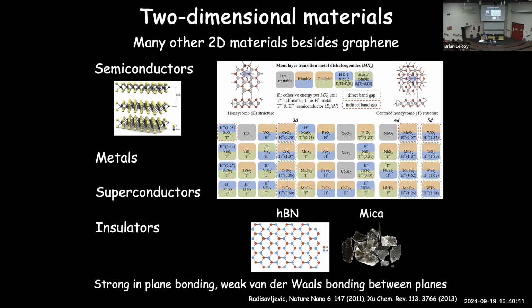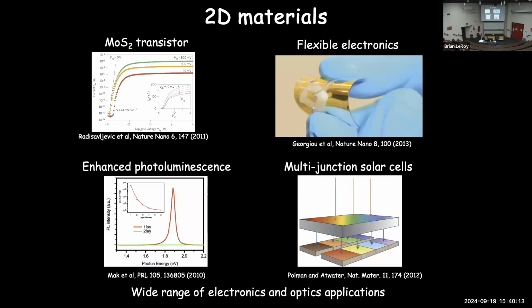And so with this wide zoo of materials, that has led to a wide range of electronic and optical devices using these materials. The graphene I showed you before does not work very well as a transistor. It's not a good semiconductor, but if you take something like molybdenum sulfide, which is a good semiconductor, you can have very nice transistor behavior. You measure the current here as a function of some gate voltage. You have 10 to the minus 13, and you turn it on here, 10 to the minus 5, so you get like a 10 to the 8 change in the current through the device with a small gate voltage change.